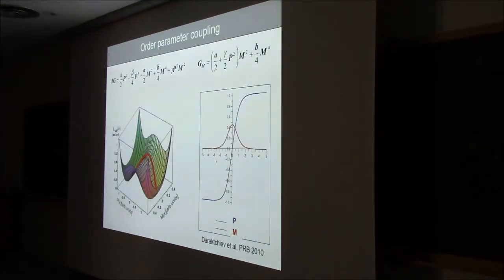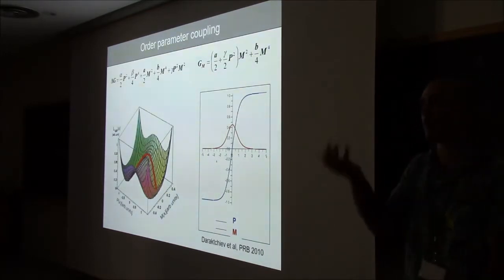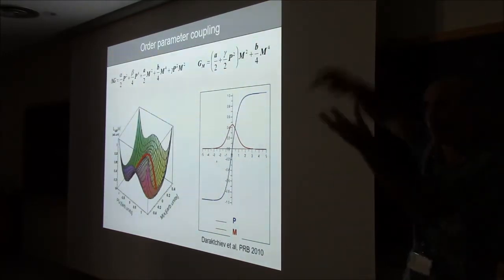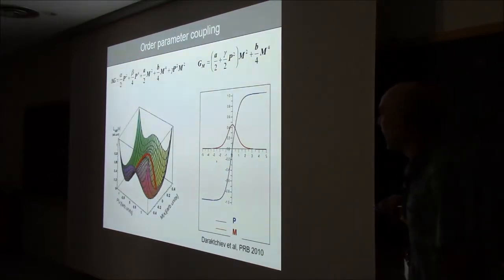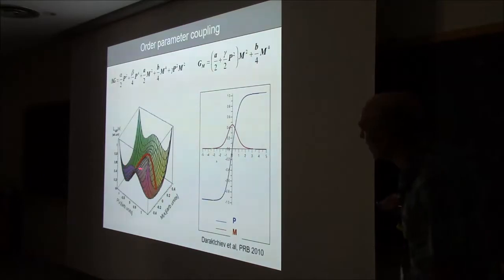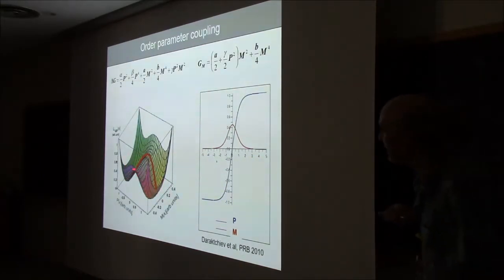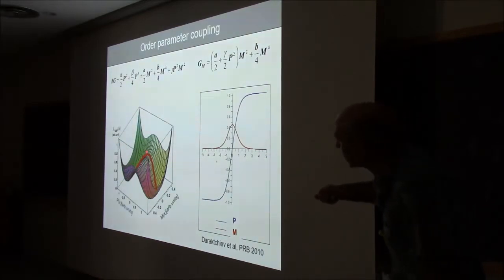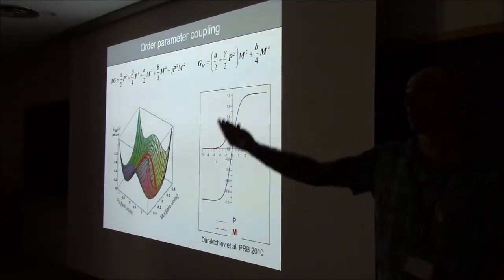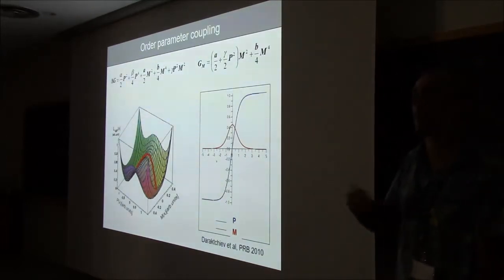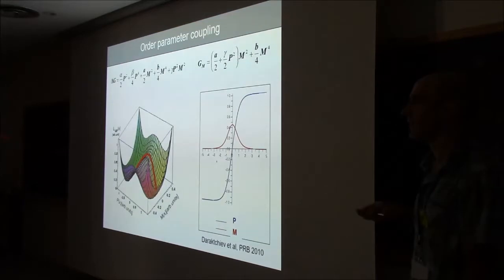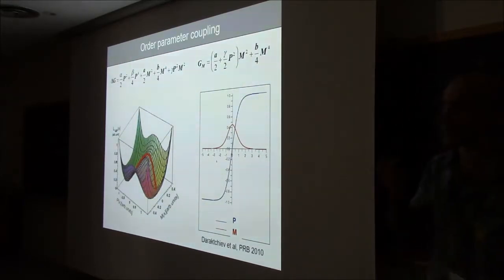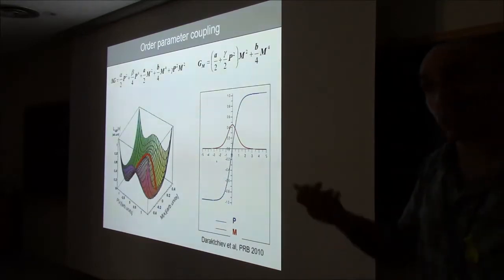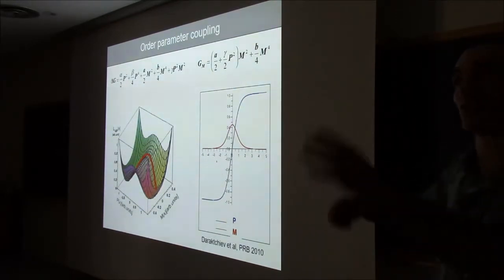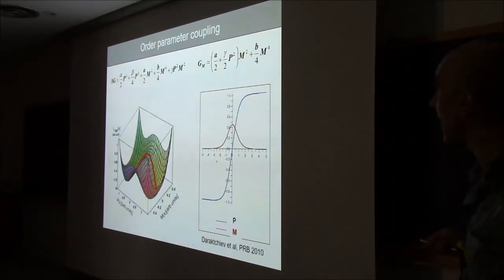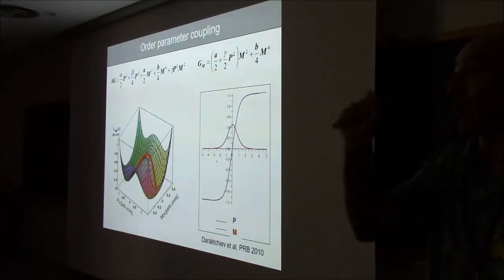You can get more sophisticated because there may be more than one order parameter in your material. It can be ferroelectric and ferrodistortive, when you have octahedral rotations, or magnetic. And when you transition from one polar state to the other, you may take a detour in the free energy space. You may take a detour along a path where the secondary order parameter, which was suppressed, can emerge. Again, you can calculate all of this from Landau theory, but this is to say, in multiferroic materials, and most ferroelectrics are multiferroic because they're also ferroelastic or ferrodistortive or have a suppressed ferrodistortive phase, you can have emergent properties that exist only in the domain wall. And this is very exciting.